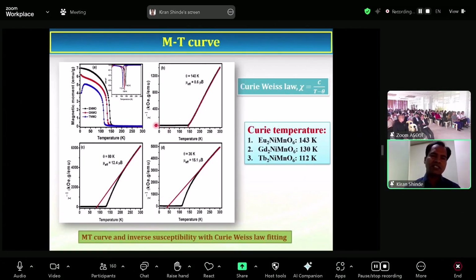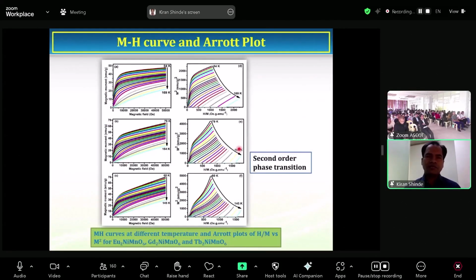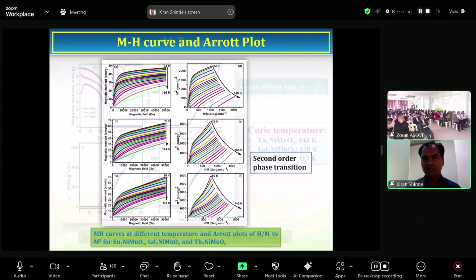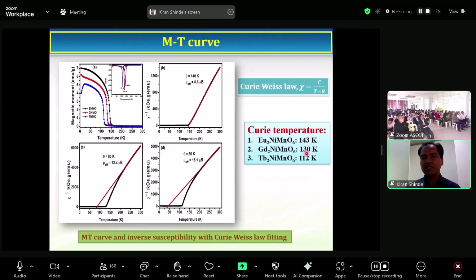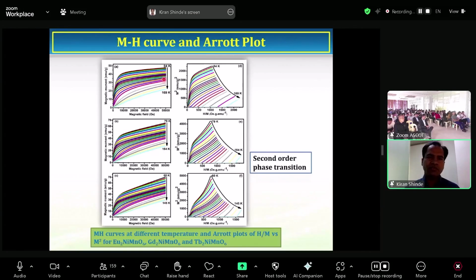And here we can see the inverse susceptibility with respect to temperature, and we determine the total effective magnetic moment of the particular material. Then to determine the magnetic entropy change, we have to measure the MH plot, like this magnetic moment with respect to magnetic field at different temperatures. So we determined the Curie temperature for the particular compounds: 143 Kelvin, 130 Kelvin, and 112 Kelvin. So to determine the magnetic entropy change, we have to measure this MH plot at these temperatures. On the right hand side of this slide, we can see the Arrott plots for these three different compounds. So the slopes for these Arrott plots all are positive.